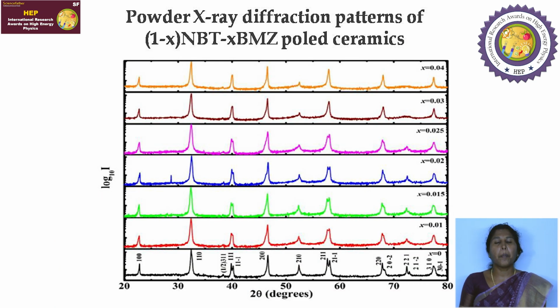This figure shows the powder X-ray diffraction patterns of (1-x)NBT-xBMZ poled samples. Here the pattern is given for various mole fractions of BMZ. BMZ is substituted from 0.01 mole fraction to 0.04 mole fraction. From this, the figure shows that all the peaks were indexed. No impurity peaks or unindexed peaks are seen in all the samples. This reveals that all the synthesized samples are phase pure and retain a single phase.